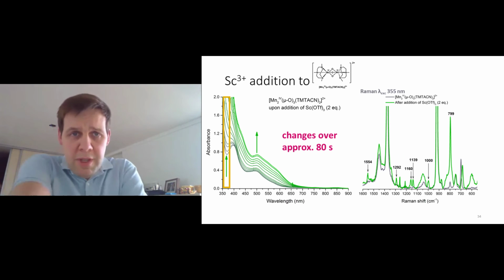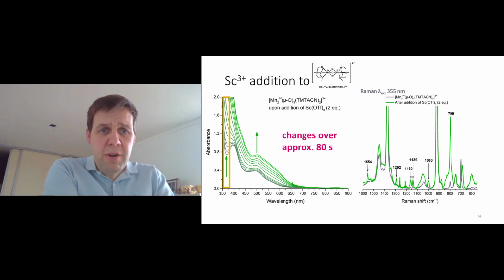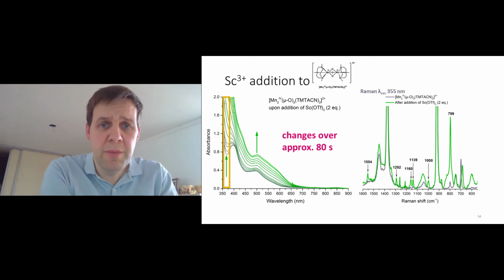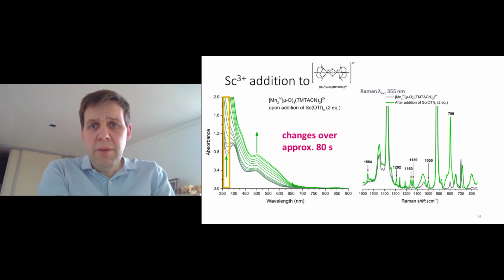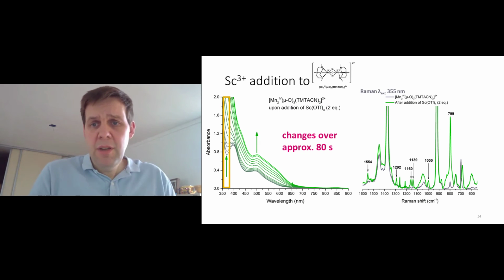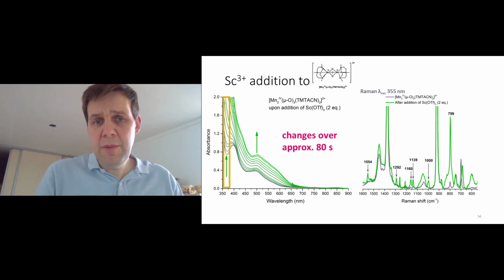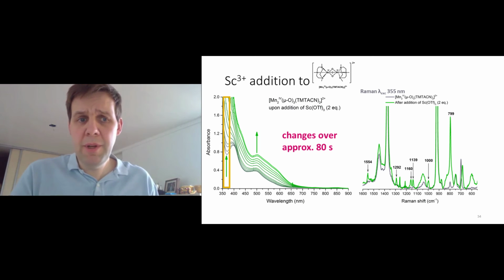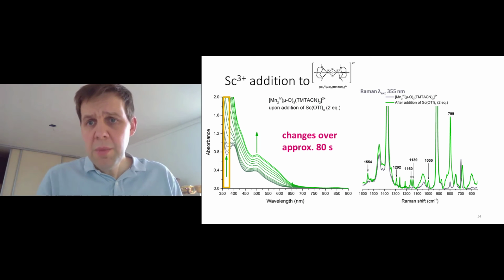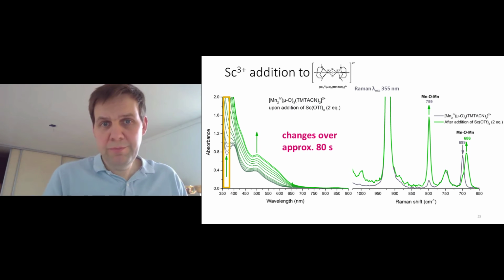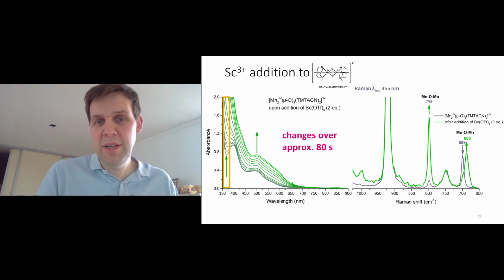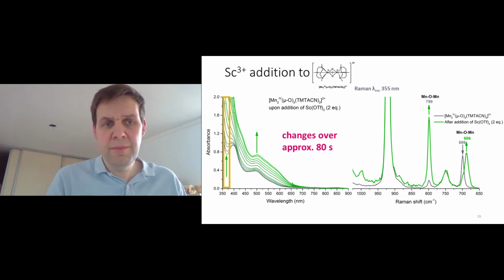So if we follow by UV-vis what happens when you add scandium to the complex, you see very dramatic changes in the absorption spectrum over 80 seconds. If you follow the Raman spectrum over the same period, you see there's very large changes to the Raman spectrum as well at 355. So there's something happening in the complex. But note that those changes take about 80 seconds, I'll come back to that, they're not instantaneous. You can see really clearly there's one band which goes down, another band goes up, and one band goes up very strongly in intensity.